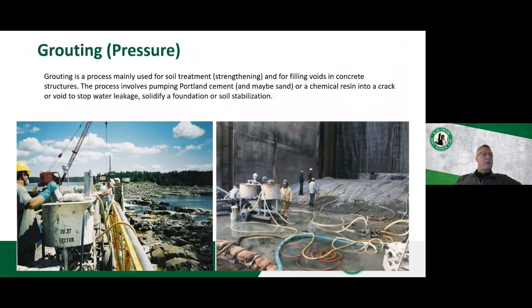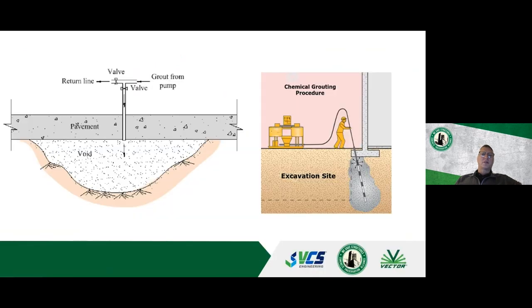Let's talk about grouting. We have about 12 minutes before we start getting into questions, so we may have to cut some down. Grouting is fairly simple. I mean, you get many different kinds. It could be a Portland cement, a sand mixture, if you're doing a cementitious one, or you can also use urethane grouting. And so if concrete has voids underneath of it and you're applying loads, we talked about it, it's going to crack. So by drilling through and installing packers, we can install large amounts of void fill materials, either urethanes or cementitious materials, and be able to fill those voids.